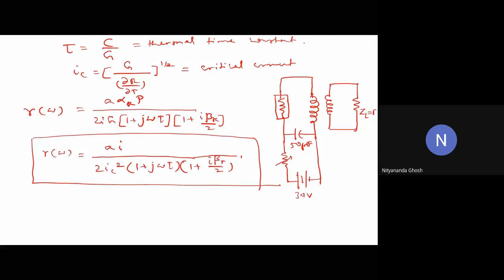So in the low frequency, low current limit, the impedance is going to have a typical functional dependence with temperature, and the existence and location of the peak in this functional dependence would be found out by equating the temperature derivative of this impedance to 0. There is some more algebra required in between, but because it's not a blackboard kind of discussion, it becomes a little difficult to engage everyone. I'm not able to see all of you while I'm writing, so I'm not sure how effective this is. In a classroom like scenario, this would have been much better.